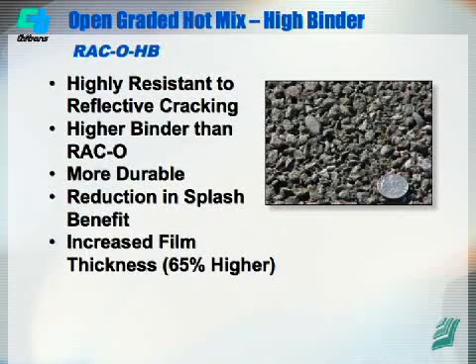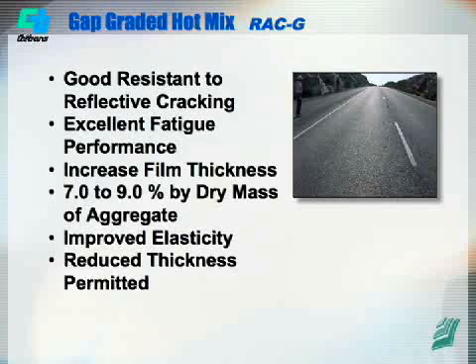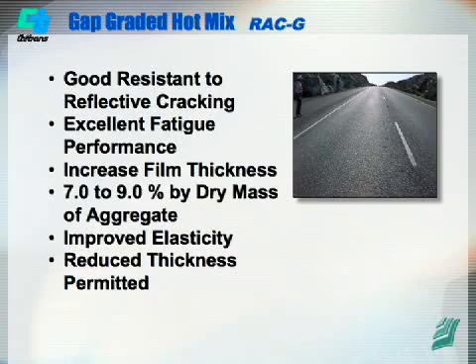Open-graded hot mix, the high binder, which I mentioned, has 65% higher binder content than the conventional open-graded. It's much more durable and much more resistant to reflective cracking. The gap-graded rubberized asphalt concrete is also very resistant to reflective cracking. This has been used in our rehabilitation program as well as in pavement preservation. Typically, the pavement preservation thickness is about 25 or 30 millimeters. They are very thin surfaces.